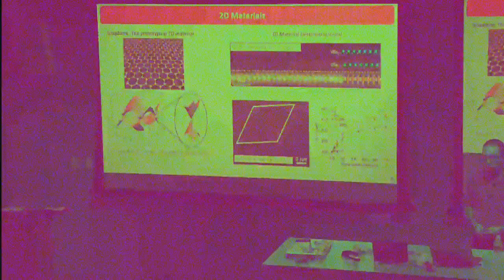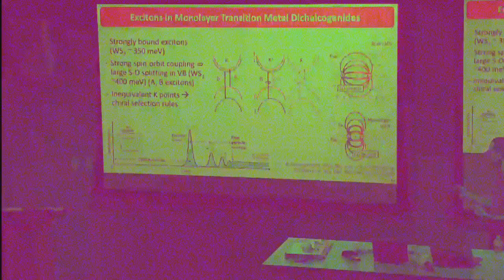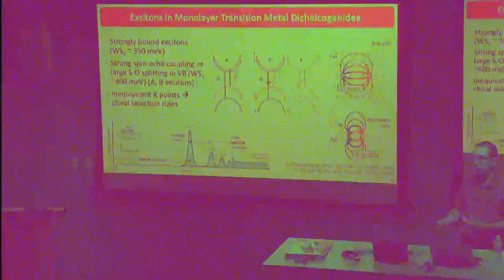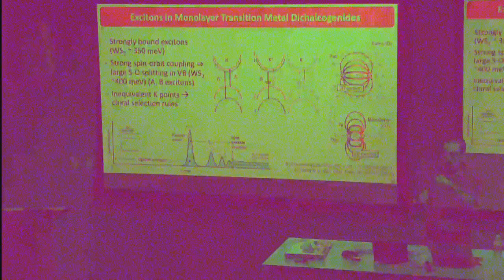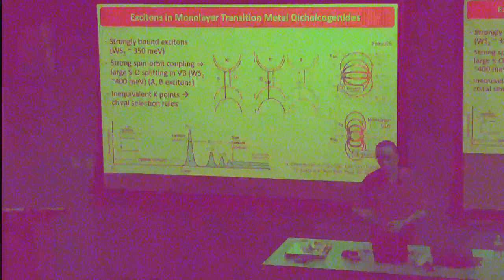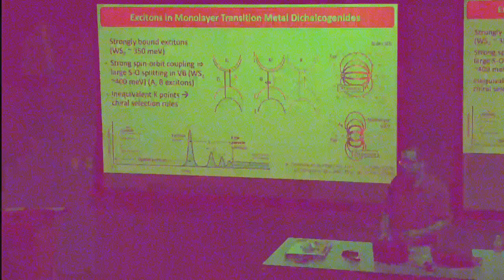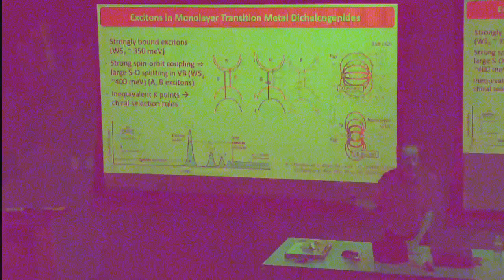Another attractive feature: because of the 2D nature of the material, you have less dielectric screening between electrons and holes, so you can have excitons — bound electron-hole pairs — with very strong binding energies. Normally you'd think excitons require low-temperature semiconductor physics, maybe 10 kelvin in a GaAs quantum well, but these things are bound by up to almost half an eV. They're totally bound at room temperature and in principle optically addressable as nice quantum states.